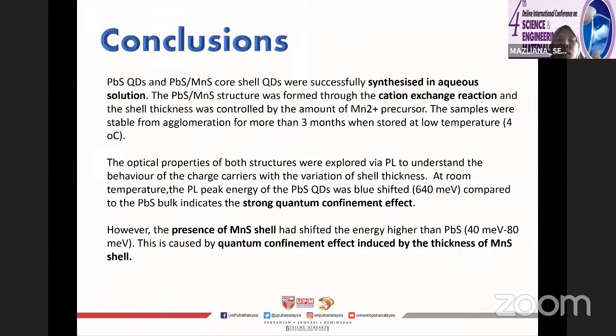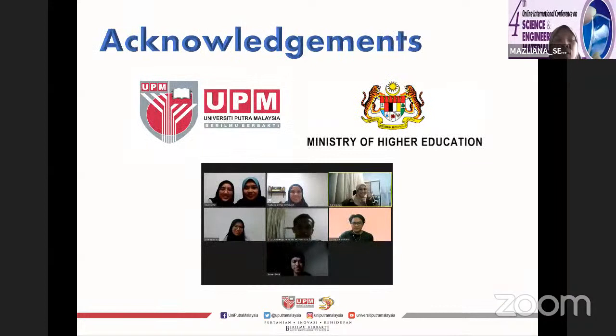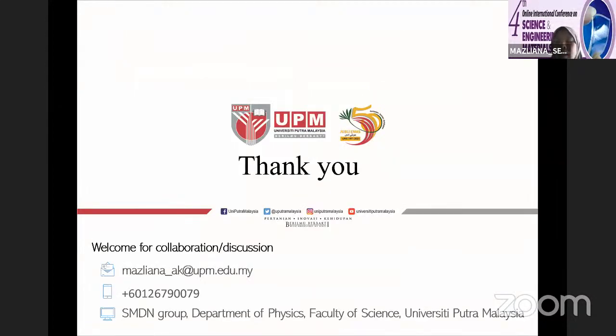So to conclude my presentation, I would like to say that our synthesis in aqueous solution is successful, and we formed the core shell by using cation exchange reaction, and the samples, we can prevent the agglomeration up to 3 months. And from the PL, we can see that there is a strong confinement effect when we change the thickness of the shells. So I would like to acknowledge UPM and Ministry of Higher Education for the grant, and I would like to thank my students for the hard work on the synthesis of the quantum dots. That's it. Thank you. I welcome collaboration and any discussion.